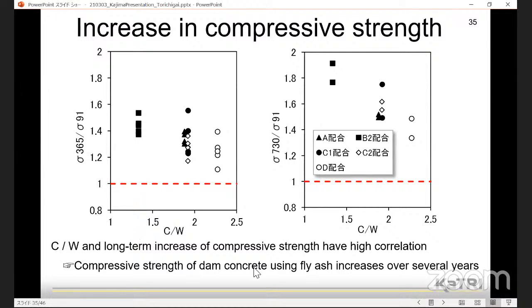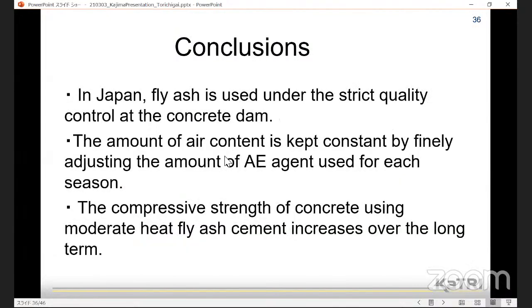The cement water ratio and the long-term increase of compressive strength have a high correlation. And here, the compressive strength at 2 years is about twice compared to the 91 days compressive strength. Compressive strength of dam concrete using fly ash increases over several years, especially at high cement water ratio. That's the conclusion of my presentation.